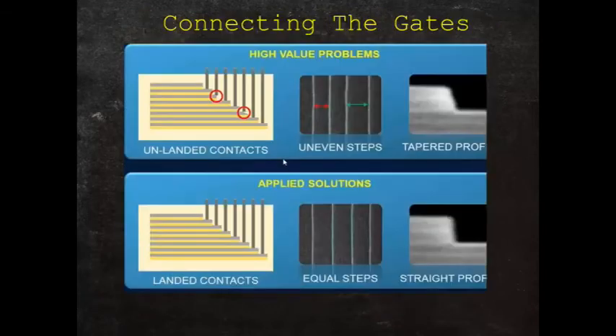What are some of the manufacturing problems with connecting the gates? It can be difficult because some of these gates, when they're litho-etched to make the stair-step, the stair-steps can be uneven. You may have wiggling on this face. You may have slanting of the gates as they come in. And what happens is that makes it very difficult to land the connectors in appropriately. This one's missing a step. That one's missing a step.